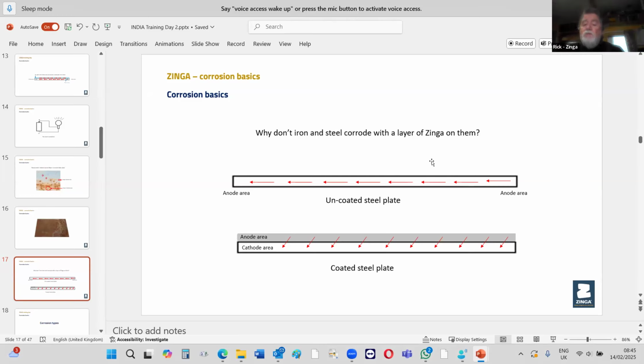No. What actually happens when you put the zinc on, because it's an active coating, it's pumping in the electrons. If you put a layer of paint onto the top of the metal, all that's doing is stopping the moisture from getting to the surface. And also the oxygen helps the reactions work quicker. But as soon as you put paint on, this is what we call the barrier coatings, because all they're doing is acting as a barrier to the moisture. If there's no moisture, there's no current. It's as simple as that.